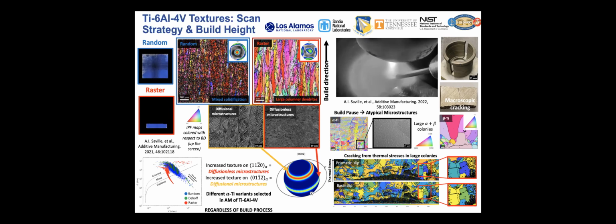We also were able to relate this to the as-built microstructures that we see. And we notice from the different texture components that if we have increased texture on the 1,1 bar 2,0 type of plane, like that shown here at the equator, we tend to see more diffusionless microstructures. Whereas if we have increased texture on the 0,1 bar 1,2 at the 45, we tend to see more diffusional microstructures. Why is this important? We're selecting different alpha Ti variants in additive. We're able to basically screen for, or it suggests we can screen, the as-built condition. And by doing that, we're able to sort of back calculate all the way up to the as-solidified microstructure and really know a lot about our microstructural state.